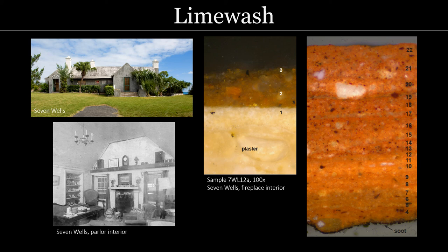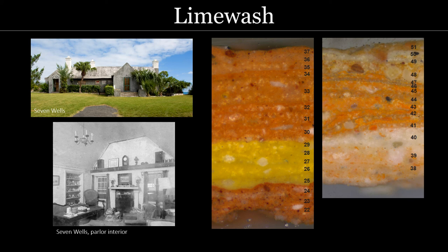Now, the sample was so thick, it fragmented into multiple pieces, so I had to cast each one individually and number the sequence of layers that way. And the sample continues. So we have these deep reds, oranges, bright yellows, pinks, peaches. These are all made by combining iron earth pigments with lime wash.